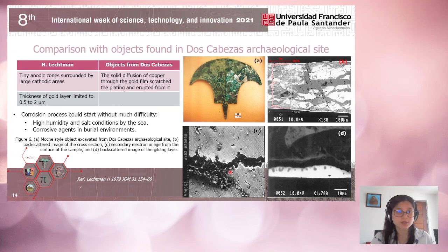Regarding the thickness, Heather Lechtman described about 0.5 to 2 micrometers for the gold layer. But as you can see from figures 6b and 6d, the thickness of the gold layer that was found in Dos Cabezas was about 10 micrometers, which is more than the one Heather Lechtman reported with this technique.